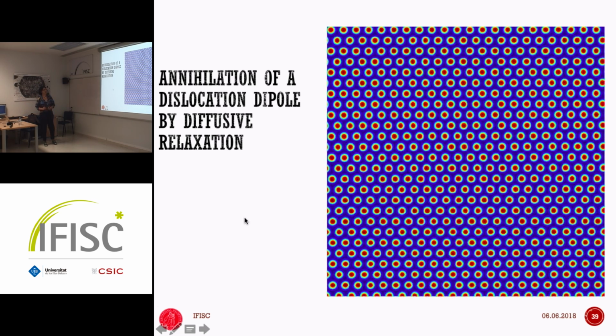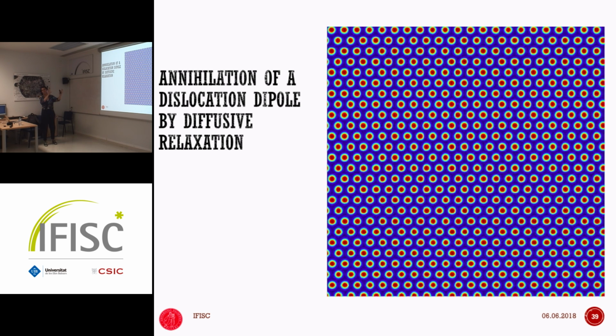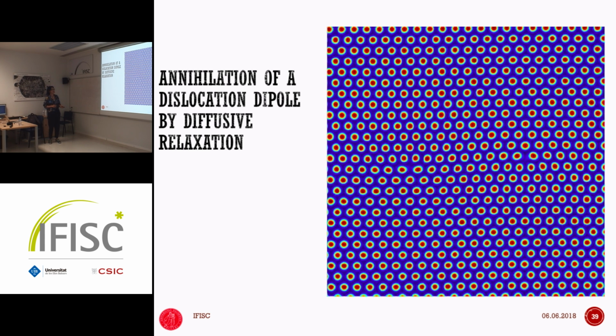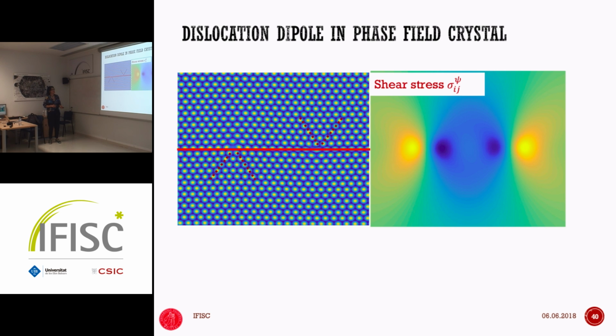Poof. And then there's still a lot of relaxation afterwards. But you already see that there's almost like a flow around it, like a honeycomb straw. This is very different than what happens in an actual crystal, where you constrain the stress to be at elastic equilibrium at all times.